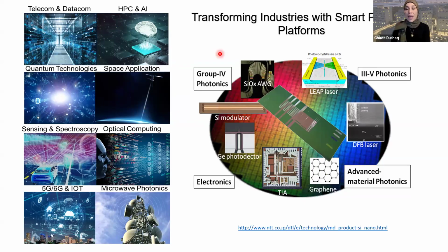So, with all that established, if we look historically at how silicon photonics started, it was very welcomed because it can be very adaptable with the silicon technology, and you can co-package electronics and photonics in the same platform. So if we look at this wafer that I got from IMEC, however, we could see that, of course, it's adaptable, but silicon in reality is not a great photonics material.